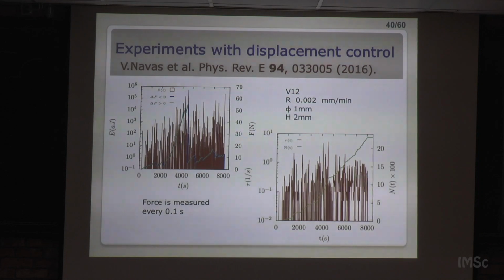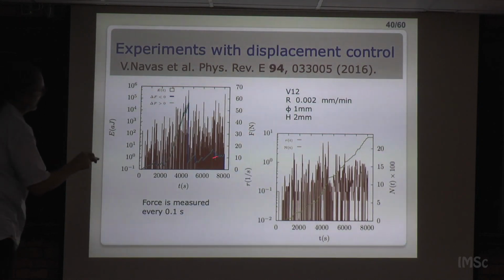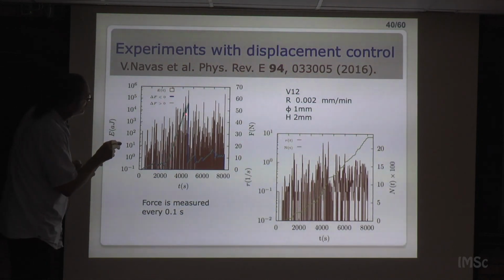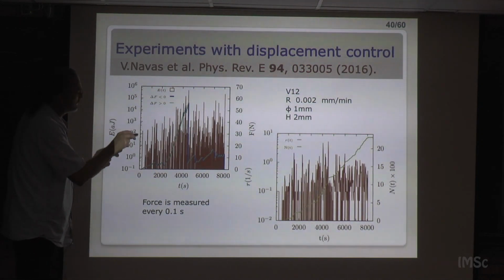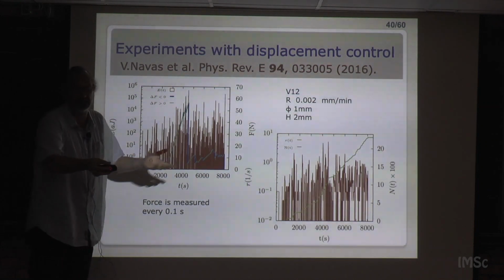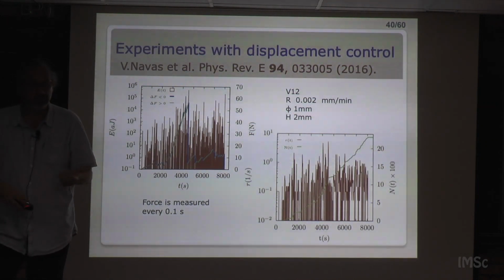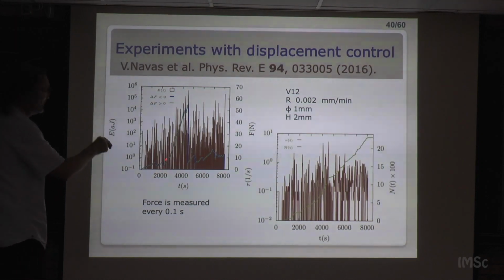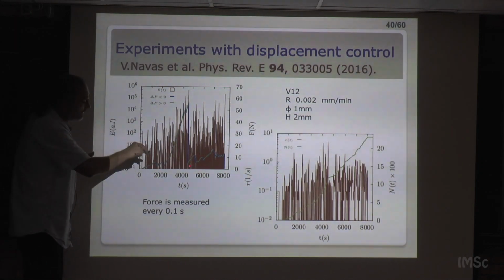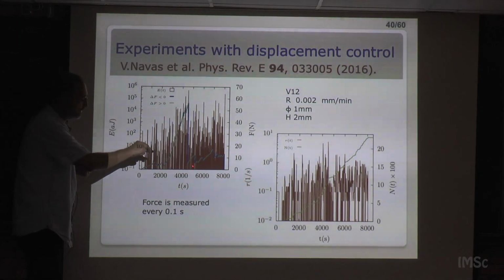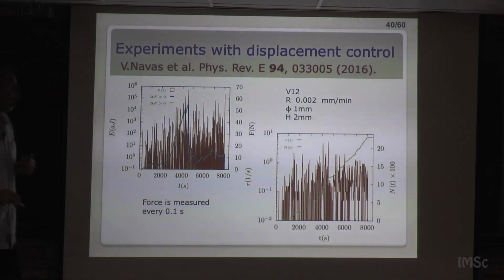Okay, now I have some extra things, like for instance, what happens when you have displacement control? So you keep the speed moving, then what you get is this force. Well, you cannot see it very well, but it's this force. You see this line? This is the force as a function of time. Time now is x, because x is proportional to time. So this is displacement and force. You see that there are these events, and there's a big one, but it keeps going here, you see, keeps going, okay?